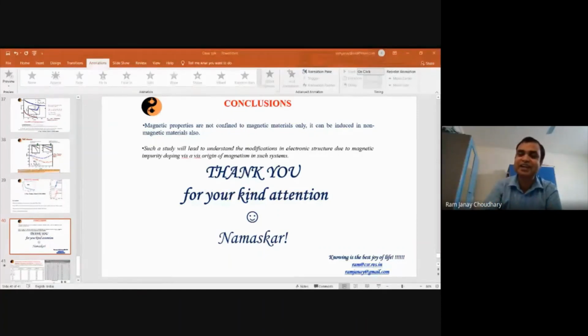The hysteresis arises because in the presence of magnetic field, your domain wall volume or the domain wall dimension increases, and when you reverse the magnetic field, it encounters certain imperfections, certain defects, and across those defects, your magnetic flux lines are pinned. And to overcome that magnetic flux lines pinning, you have to apply extra magnetic field. And therefore, you have a lagging between the magnetization and the magnetic field. And because of that, you have a coercivity or you have a hysteresis behavior.